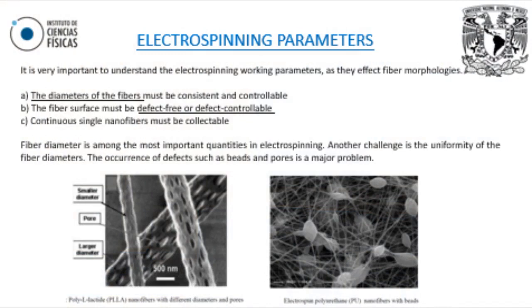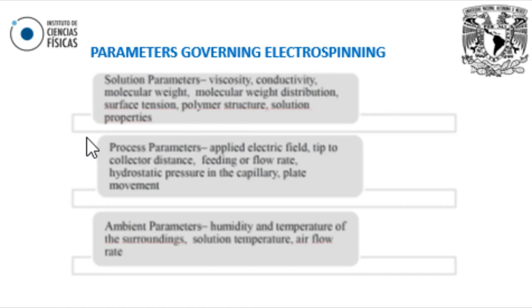What are the parameters that govern the nanofibers? We have a lot of parameters. Solution parameters concern viscosity, conductivity, molecular weight of the polymer, molecular weight distribution, surface tension, polymer structure, and the properties of the solution. And if you look at the process parameters: how much electric field, how many kilovolts you apply to the polymer, the tip to collector distance, flow rate, hydrostatic pressure, plate movement, and ambient conditions like humidity, temperature of the surroundings, solutions, and airflow rate. Everything is very, very important.